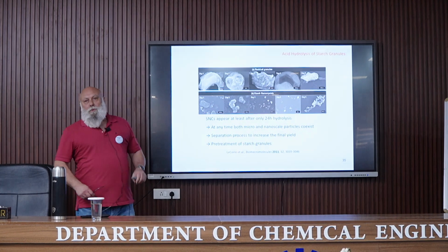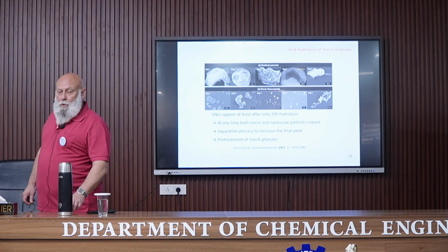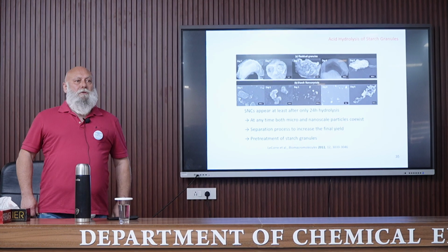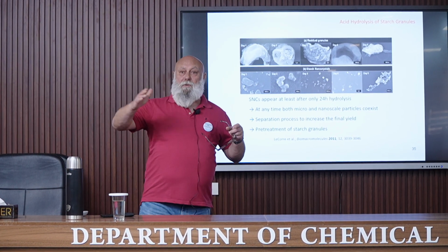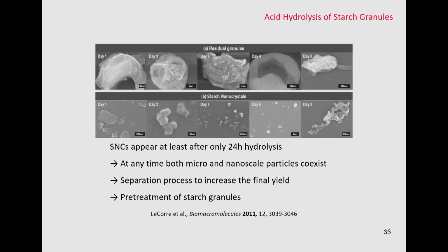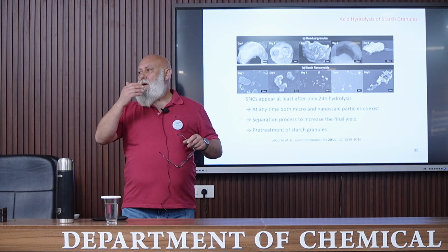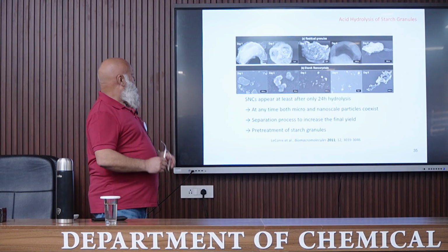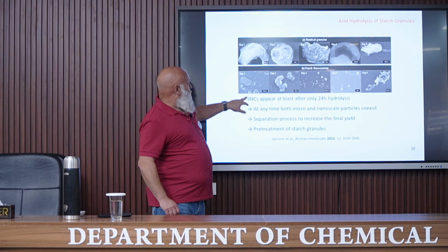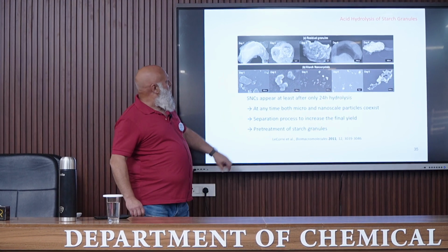So just to come back to the starch nanocrystals, you have seen that the duration of the treatment is quite long. The yield is low. And this is due to the fact that because of the long duration of the acid hydrolysis treatment, during the first day, some nanocrystals are produced, but during the extended hydrolysis time, they disappear. They are completely dissolved, even if they are crystalline. And we can see this here.